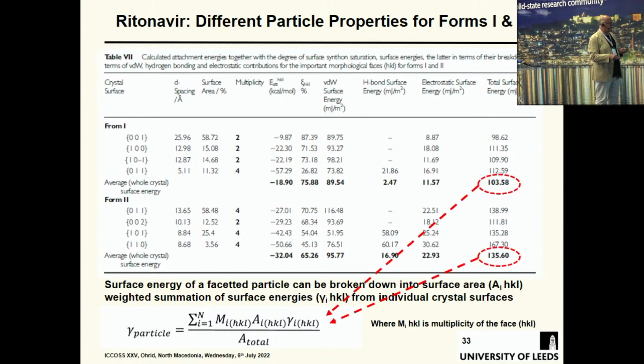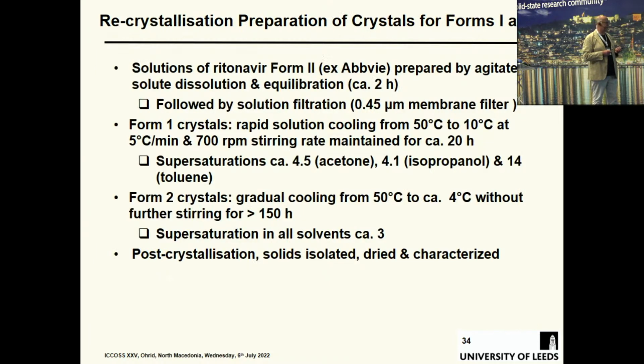You can calculate a weighted surface area. So you calculate the surface energies of all the individual faces, and then you weight them by their multiplicity and their area, and you basically get a surface energy of the particle. And getting the surface energy of the particle gives an important parameter for how it might process.